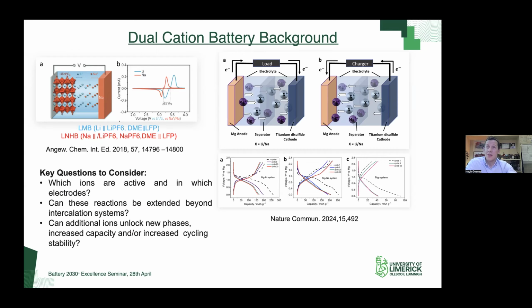So there are a lot of questions to consider there. Which ions are active? In your dual ion systems, the magnesium or the sodium are both active, and in which electrodes? In this case, you have a magnesium anode. What is the stripping and plating characteristic in that system? And what we wanted to see is, could they be extended beyond intercalation systems? You probably have plating and stripping at the anode side, but at the cathode side you're just looking at intercalation into TiS2. Thinking back to that table that I showed earlier on, can additional ions unlock new phases? All of those different theoretical capacities that I showed are linked to the formation of specific phases in those systems, where you have just a single charge carrier and the group 14 element.